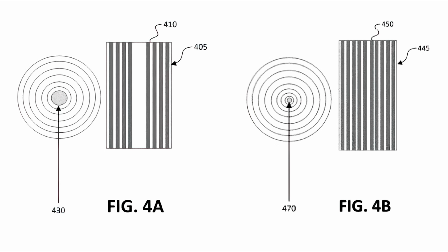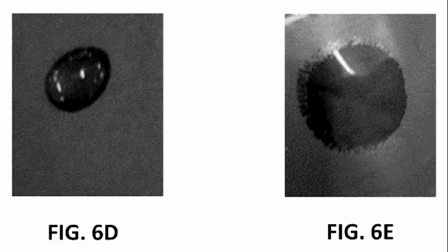Figures 4a and 4b show the benefits of plasma treatment for making the jelly roll more structurally robust. It allows the core of the jelly roll to be made smaller without introducing core collapse issues. A smaller core void in the center of the battery cell means more energy storing material and therefore greater energy density. Figure 6d shows electrolyte beading up on an untreated electrode versus 6e, which shows electrolyte being absorbed by a plasma-treated electrode.